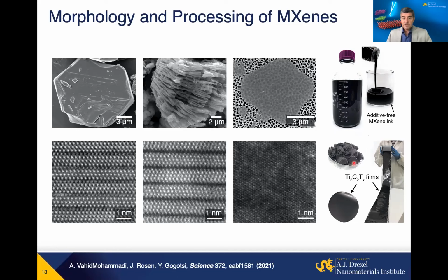And from this powder, basically, we go into solution, and from solution, we can do vacuum assisted filtration, we can strain it here. But you can also, instead of HF or in situ HF formation, lithium fluoride, HCl, or similar agents, you can use also molten salts, chloride, for example, eutectic salts. And in a similar way, etch the material, then your surface termination will be, say, chlorine or bromine, not oxygen here. So those are the chemistries currently involved in the synthesis here. But in all cases, we end up with a powder that can be delaminated into single flakes afterwards.